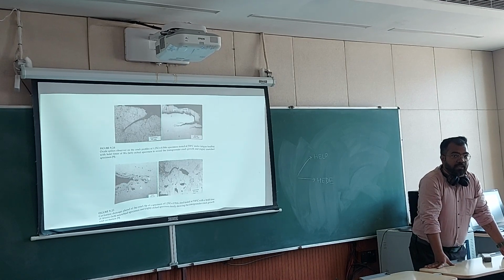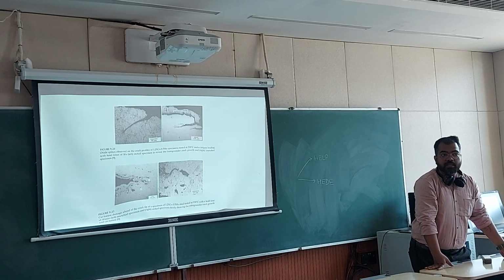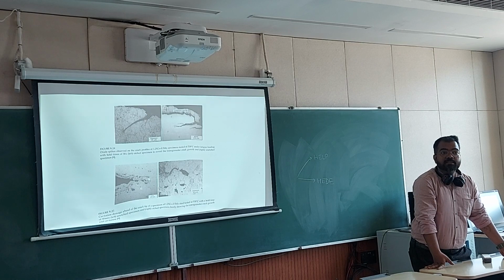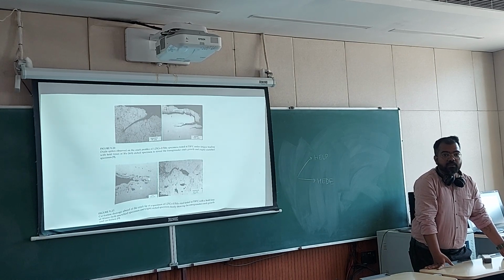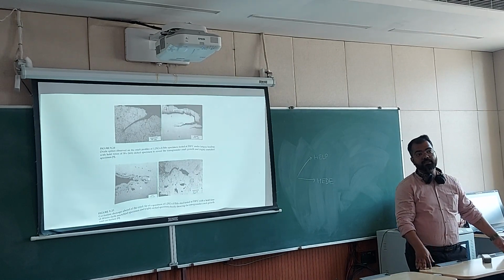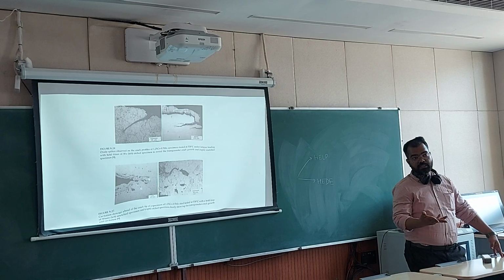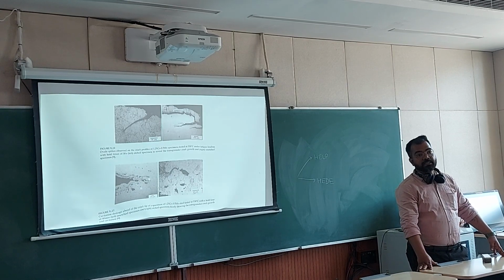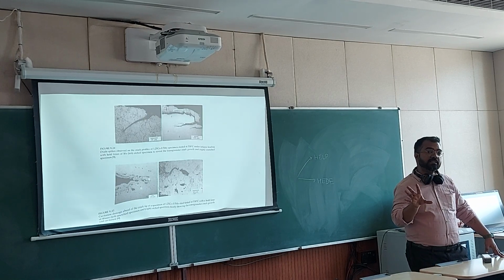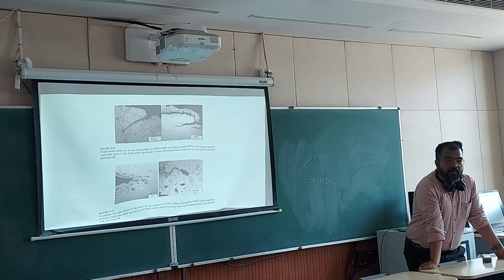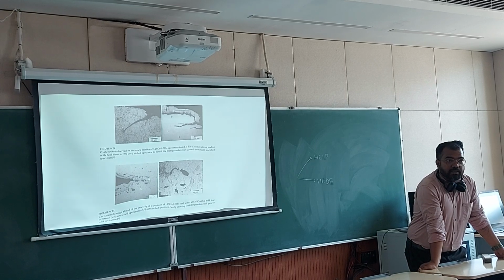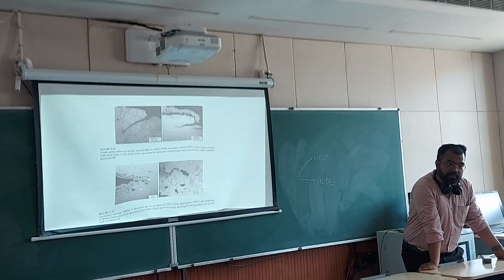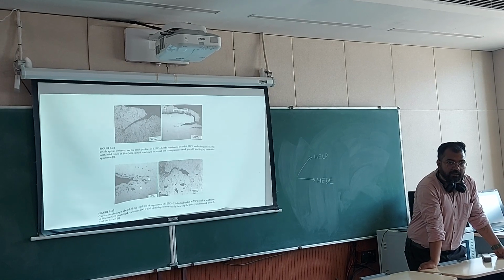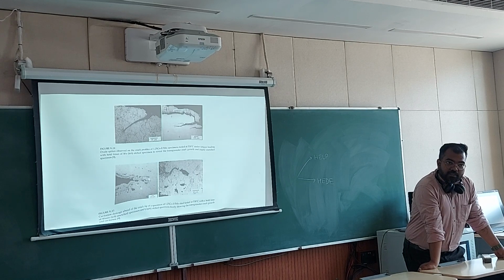So modulus interaction will happen here, and hydrogen will decrease the shear modulus of the material. By decreasing the shear modulus, it will enhance the plasticity locally, okay? And this local plasticity enhancement will cause softening of the material locally. So this is not going to give you a lot of problems. It is just dropping the strength locally, right? But this goes hand in hand with HEDE, which is hydrogen decohesion. In that case, hydrogen causes the material to break because of the decrease in the strength of the material by interacting with the dislocations. Okay, and this goes hand in hand. So HELP and HEDE will go together, and that will cause problems.